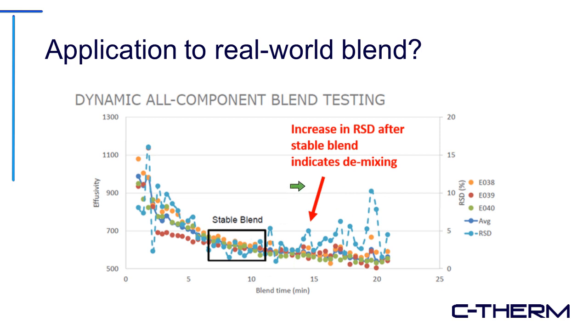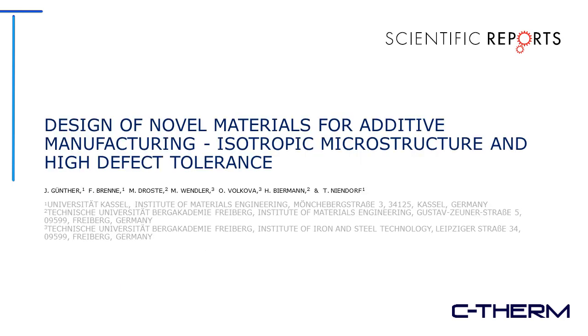And this kind of increase in the relative standard deviation between the sensors indicates that there's a greater difference in regional variability between the 3 sensors that were in the lid of the blender. And that indicates that we're getting some sort of segregation or deblending phenomenon occurring. So we're getting some demixing. Looks like it demixes a bit, and then it goes back in. Then it demixes a bit and goes back in, demixes a lot, goes back in. So this is actually a case where it's an unstable blend, but you can recover if you overblend. So this is a better case scenario than one that is simply unstable and won't go back after it's destabilized and segregated. Going over to the next one.